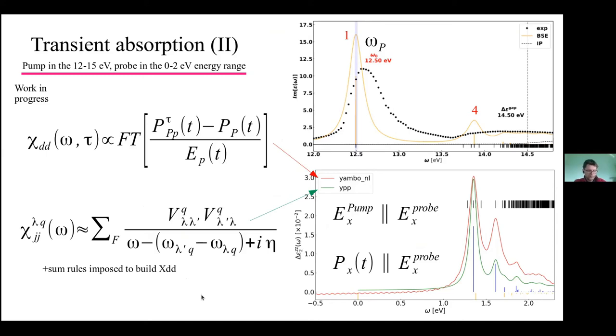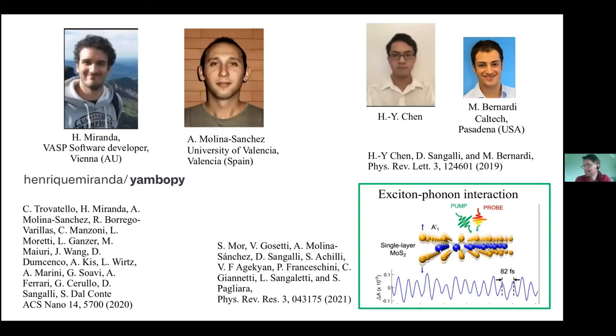Now, for the last part, I want to jump from exciton-light to exciton-phonon interaction. I will quickly discuss an analytical formulation of exciton-phonon coupling done in collaboration with Marco Bernardi, with most of the work done by Chen, a student in Marco's group. I will also show results on how one can define exciton-phonon coupling by finite differences, in collaboration with experimental groups. For exciton-phonon coupling, the expression of the exciton-phonon coupling matrix element is very similar in structure to the exciton-light coupling: one replaces the dipoles coupling electrons with light with the electron-phonon matrix elements. Exciton-phonon coupling is much more involved than exciton-light coupling because the phonon momentum enters as well, along with the exciton momentum. So one needs excitons at finite momentum and must account for scattering from one wavevector Q to another Q'. With this coupling, it is possible to compute exciton-phonon lifetimes via a Fermi golden rule expression describing scattering from an exciton at state lambda to another exciton at lambda' via a phonon. For example, for HBN, taking an exciton at the minimum of the excitonic dispersion, one gets a very short lifetime.